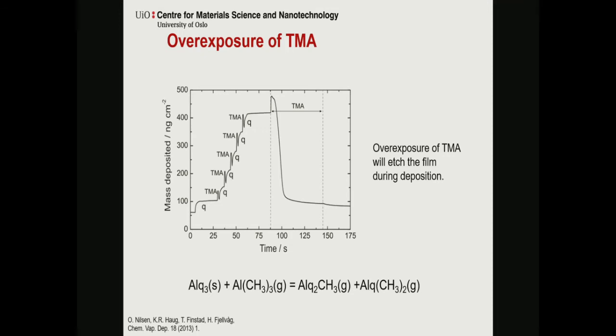Strange. You can actually lose film. So this is a pulse of your 8-hydroxyquinoline, trimethyl aluminium, okay, but still not too much of it. You build film, and then we just went in and shot quite a lot of trimethyl aluminium, and we lost everything.